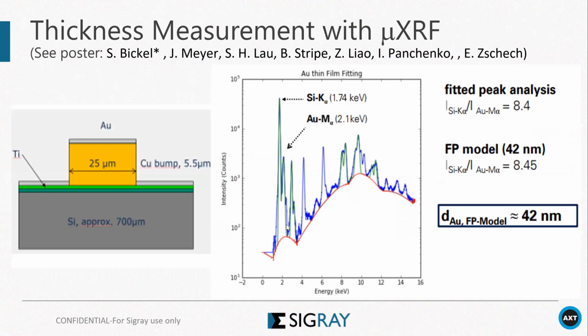One of the applications is for semiconductors here. We mapped the gold thickness on top of this structure on the left, and we do data fitting. The measurement was confirmed by electron microscope, and this was in collaboration with Professor E. Zschech from Germany.